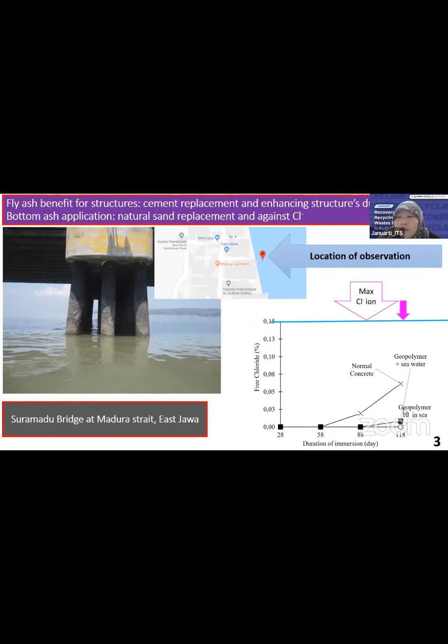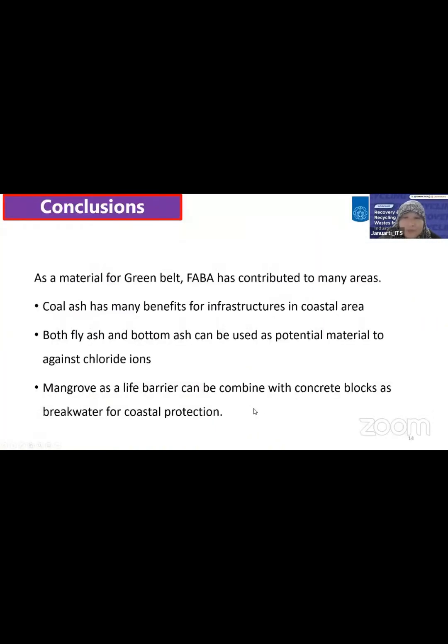So this is the very big difference in durability between the normal concrete and the geopolymer. All right, then I come up with the conclusions because I was given a very limited time. As we can see here, for the green belt of Indonesian coastline, actually fly ash and bottom ash have contributed to many areas. It has a lot of benefits for our infrastructures in coastal areas, and both fly ash and bottom ash can be used as a potential material to immobilize the chloride ion to protect our structure from corrosions. And again, mangrove as a living barrier can be combined with concrete blocks as a breakwater for coastal protection.